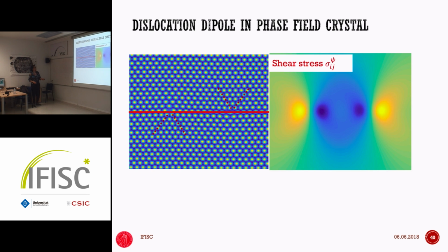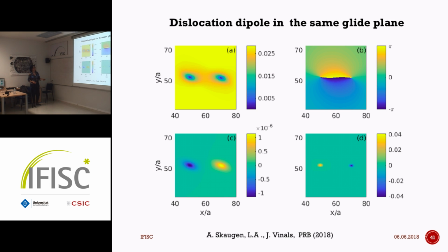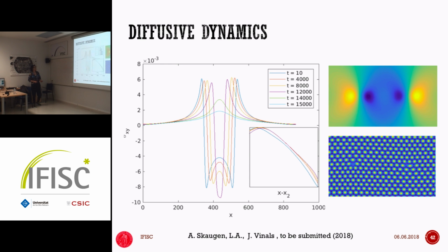For this particular case, we can also extract the topological defects when they're in the same glide, and we can show that they're topological defects because we look at the amplitudes, and this is the Burgers vector. So this is where we can calculate it and show that it's a very quantitative formula. If we make a cut through the 2D stress field along this plane, we see the profile of the stress field at various times.